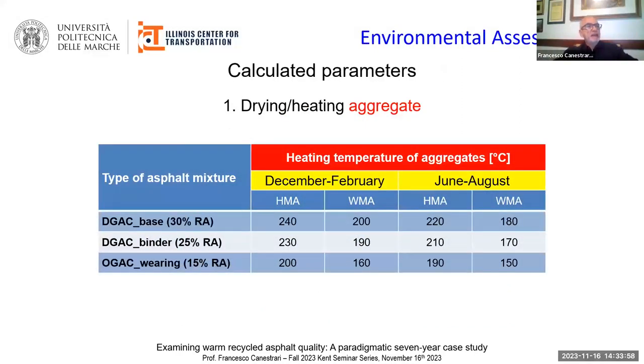During the drying and heating phase of the aggregates, different temperatures were assumed for the two reference periods. In particular, according to the data taken from the asphalt plant, which cooperated with us when we did this study, higher temperatures are adopted during the cold and the wet weather. Moreover, the higher the RAP content in the mixture, the higher the heating temperature of aggregates.